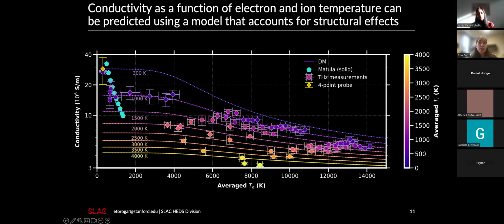We are seeing that in our cold sample, there's such a big difference from what is expected in the literature. And we knew this from the past. We knew that grain boundary scattering is relevant. However, we also observed that even as we are advancing in temperature, this grain boundary scattering is relevant for the system.